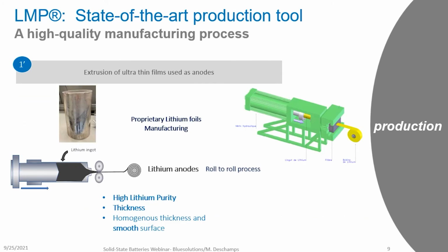Let's go to the negative side, the anode side, the lithium side. I have to mention that parts of this process are not presented here. The raw material is lithium ingots. The press extruder is used to make a film. The objective is to obtain high lithium purity with no pollution. Thickness of 20 micron is the minimum we can reach today. Smooth surface and homogeneous thickness all over the roll.